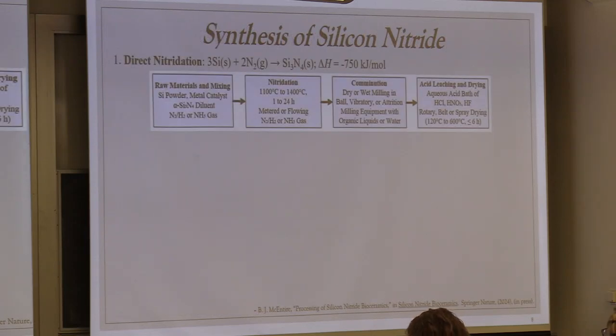Okay, to make silicon nitride powder, there are basically three methods that have been developed. The most traditional method, invented very early on, is direct nitridation of silicon. This is where you take very fine silicon powder, put it in a furnace, cover it with nitrogen gas and heat it. It reacts. You have to keep it below the melting point of silicon, so it nitrides and forms agglomerates. You have to mill that back down, and then there's a washing and cleaning step. Most silicon nitride today is produced via direct nitridation.